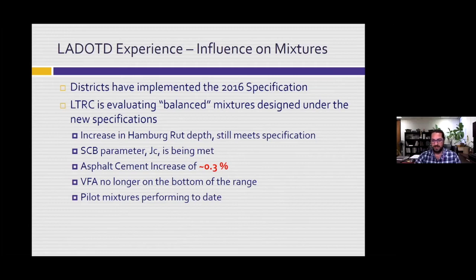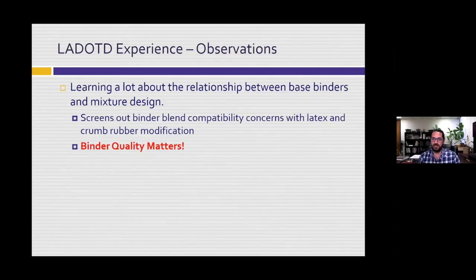Again, it's only been 5 years now, 6 years now since the pilots went down, but I have not seen any premature cracking. So one of the things we really like about this is we are a state that allows plant blending. And so we're finding out a lot about the relationship between base binders and the different components that we mix into them. And what the LWT and the SCB are both capable of doing is screening out binder blend compatibility issues. And those mainly showed up between crumb rubber and latex blends that we do at our plant facilities. And through running these tests, we're able to say, okay, this base binder is not working, or something needs to be added to this base binder to get this plant blend in place.